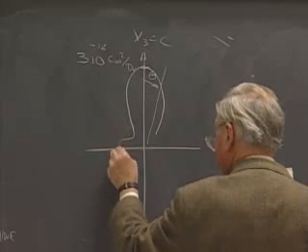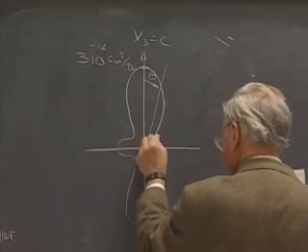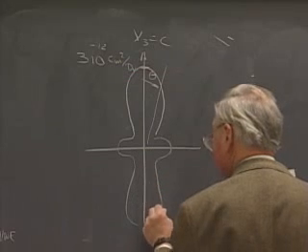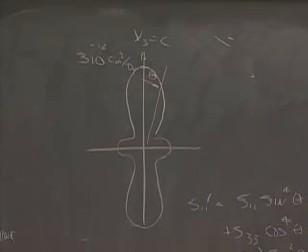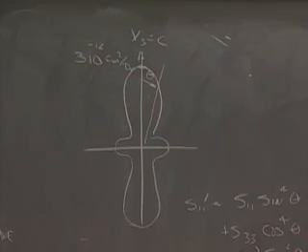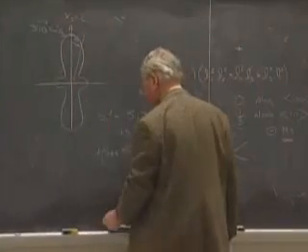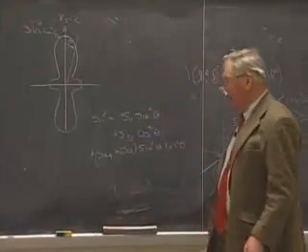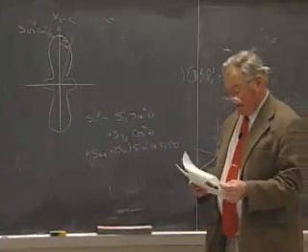And then there's a cute little wiggle just near the axis. So it looks something like that. Not a terribly isotropic surface, and a variation of Young's modulus of 3 to 1 in the direction parallel to C and perpendicular to C. So lots of exotic surfaces of this sort.